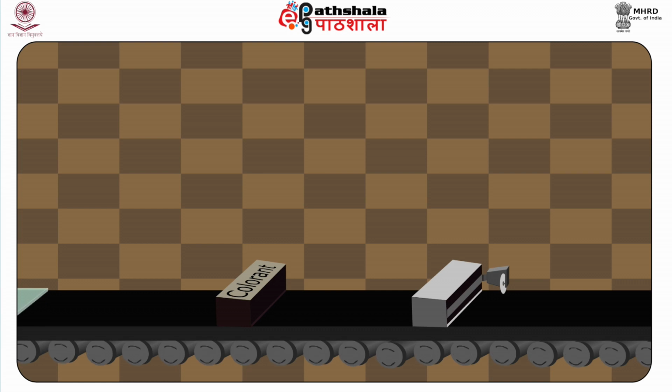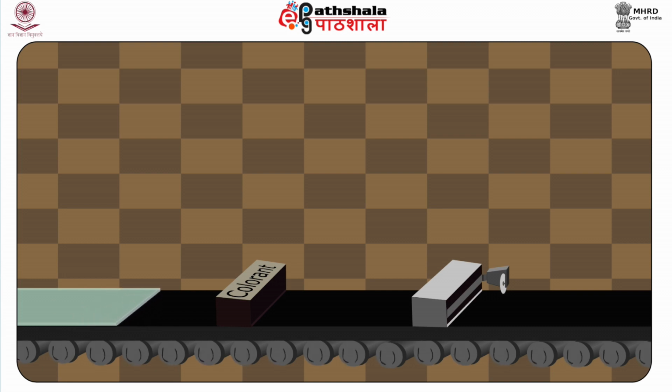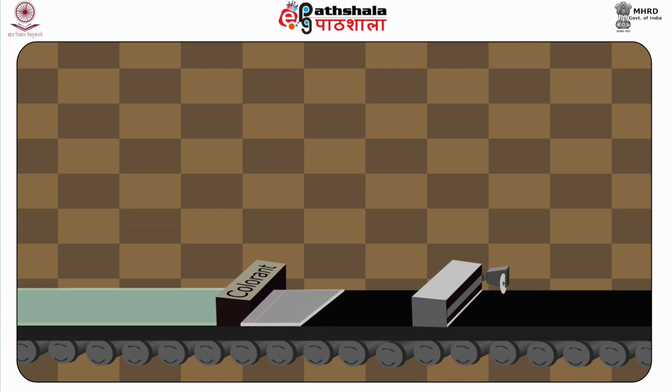Unless the raw materials are pure, glass made from silica and other raw materials will appear green, the coloration depending mainly on the amount of iron oxide and other impurities. But for some products, the manufacturers decolorize the glass by adding small amounts of colorants which are complementary to the green color so that the finished articles appear to be colorless.